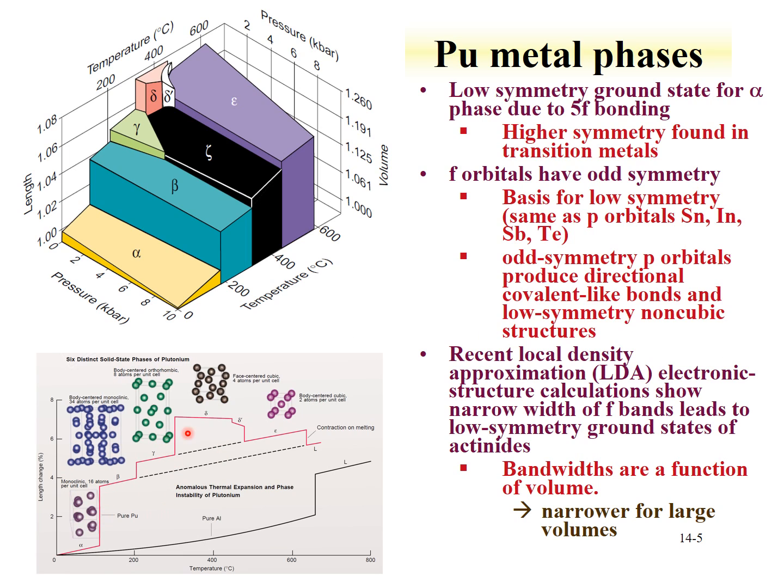This is similar to the figure that was shown on the previous slide. And we see as we get higher, we go from lower to a higher symmetry. The other thing that can be pointed out here, compared to aluminum, which just has one phase that increases in length, and then when it reaches its melting point, the density decreases, is a very simple system. Plutonium is much more complicated with these different phases, and then added to the fact that the liquid is more dense than the highest temperature solid phase.